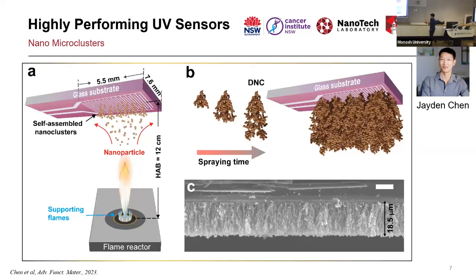One of the works I wanted to present is from my former PhD student. He's still in the group as a postdoc. What he did, he put his substrate at 12 centimeter, which gives quite a strong film. With this film, we got 18.5 micrometer of zinc oxide on the substrate, and this happens after only 100 seconds of spray. So it's a very fast technique. You put your substrate there, 2 minutes later, you have 20 micrometer of film deposited on the substrate.